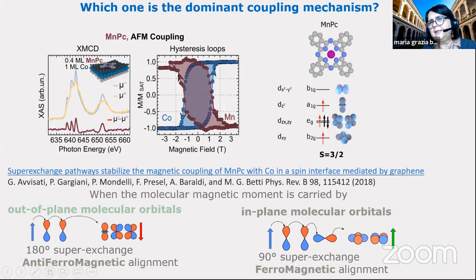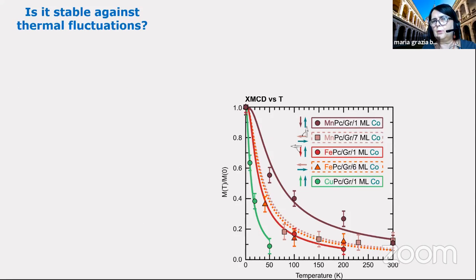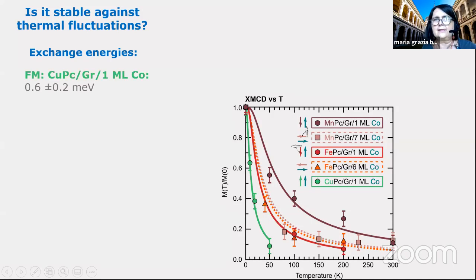So this is interesting: you change the atom in the middle and you can switch from antiferromagnetic to ferromagnetic coupling. Now, the most important question is: is this system stable against thermal fluctuation? So we make the same experiment. In this experiment, we change the temperature up to room temperature for all the systems, and then we also calculate the exchange energy.